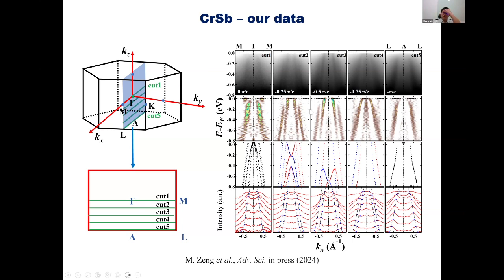The reason we didn't do a spin-resolved measurement on this compound is that we tried to do it, but it gave zero signal. We guess that's because the domain size is not very big in this compound, so maybe the domain is not large enough for us to do the spin-resolved ARPES measurement.